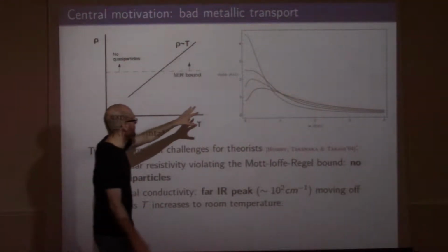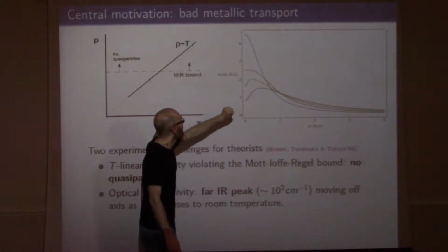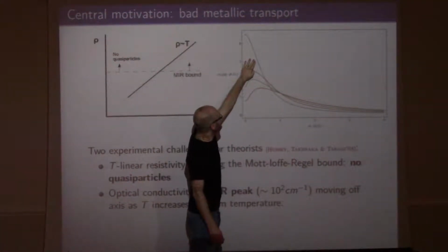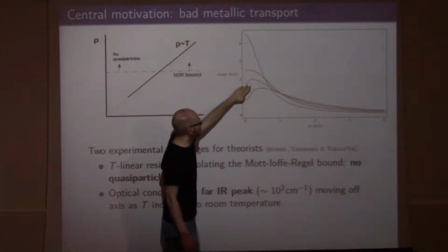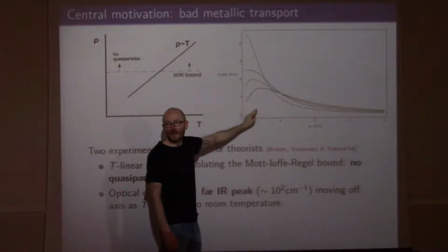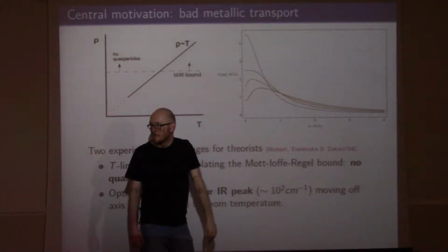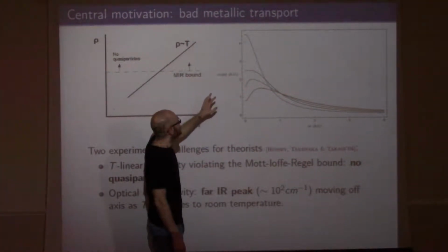And this is the response coefficient. This is what it looks like. This is at low temperatures, the blue curve, and now going down, you're increasing temperature. So the red curve is room temperature, let's say. So you see that there are two things that are happening.